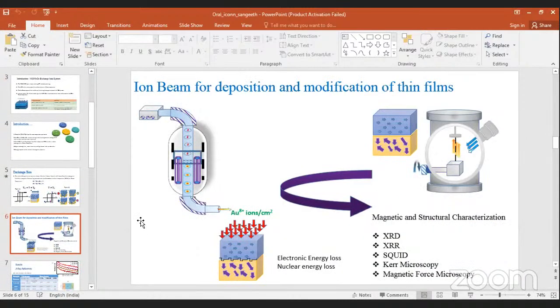In the work we have done, we used ion beam sputtering to deposit the nickel oxide, and on top of that we deposited the FeCo. The nickel oxide was deposited in the presence of oxygen partial pressure. The modification was done using swift heavy ion irradiation at the IUAC, New Delhi center. There we can change the interface and also the structural properties by swift heavy ion irradiation. Here we used swift heavy ions, which are dominated by electronic energy loss. For characterization, we mainly looked at XRD, XRR, SQUID and Kerr microscopy on these samples.